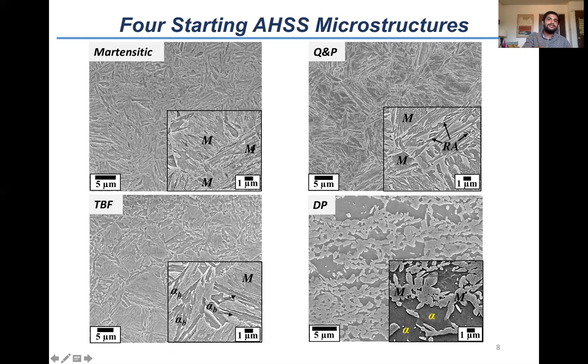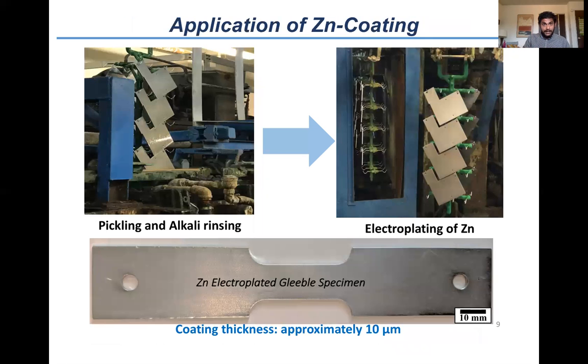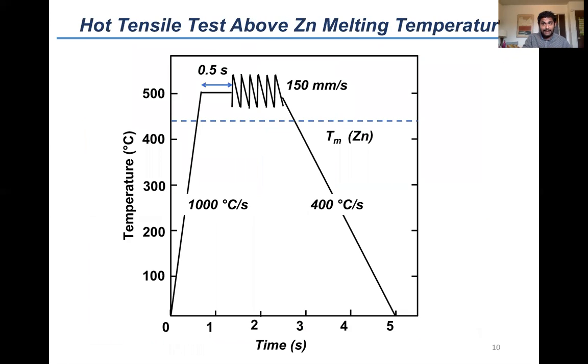So it will be very interesting to note the LME sensitivity of these 4 microstructures at a fixed composition. Now, to know the LME sensitivity, we have to first apply the zinc coating. So we applied the zinc coating via electrogalvanizing. We electrodeposited zinc on the surface of the steel, and then we did hot tensile testing at different temperatures above the zinc melting temperature. In this presentation, I'm showing the results for the hot tensile test at 500 degrees C, which is not very far above the zinc melting temperature of 420 degrees C.